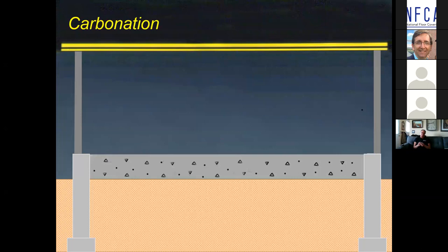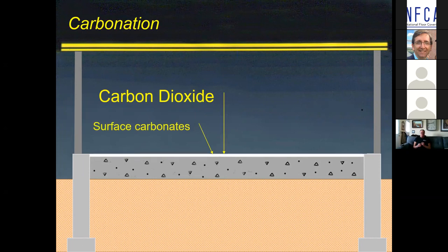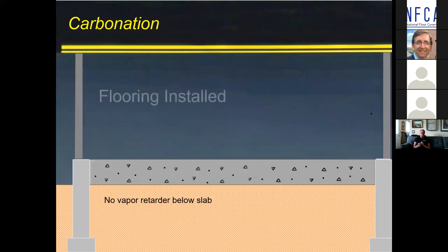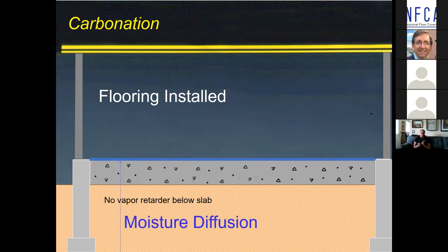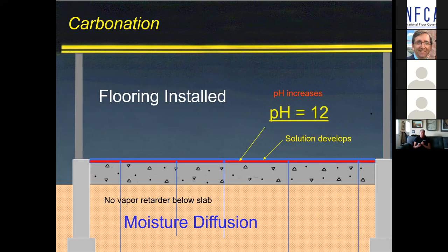Everybody is counting on, and everybody's right, that a bare concrete surface exposed to the atmosphere will experience a degree of carbonation. Chemically speaking, CO2 reacts with moisture, H2O, forms a mild form of carbonic acid, which in turn creates calcium carbonate. It lowers the pH to about 8.5 to 9. Okay, perfect. That's what we want until we come in and put down the floor covering. Now we get that moisture redistribution. And if there's no vapor retarder, or if there's enough moisture still deeper in that concrete to create a solution at the surface, the alkalis go into solution. What was 8.5 or 9 now becomes 10, 11, 12, and can adversely affect the adhesive itself.